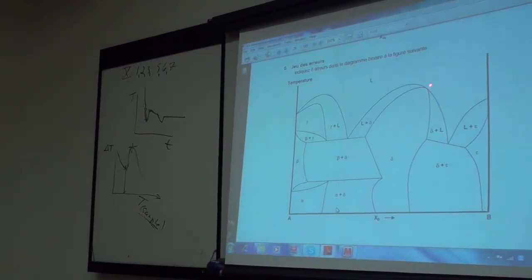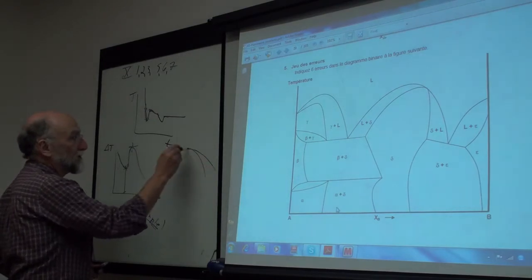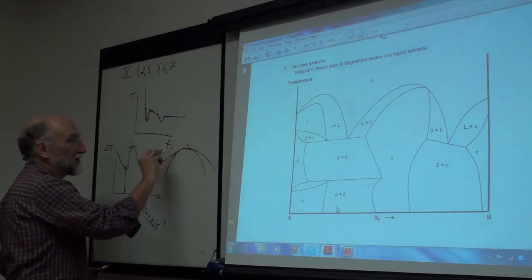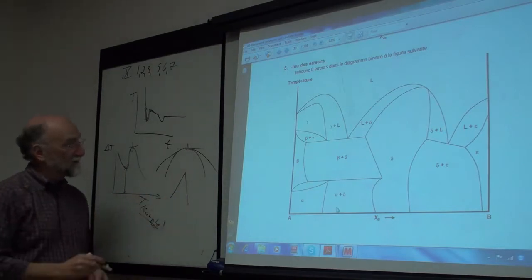This is an error because when you have a maximum in a two-phase region, the point where the solidus and liquidus contact has to be at the top, and it actually has to contact. Here the two lines don't contact, here the two lines contact, but not at the maximum. So the two of them have to contact at the maximum, and even with zero slope, as I showed you. When the two reach the maximum point, this is the maximum temperature, and both curves have a zero slope. They do not come up like that.